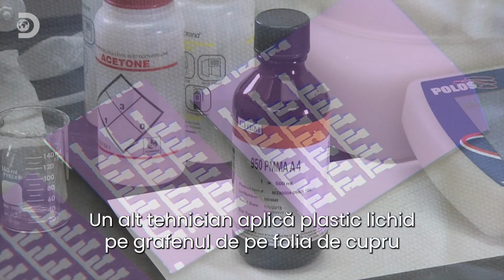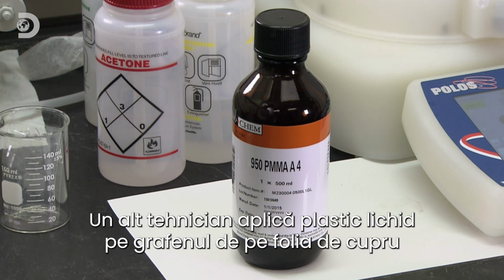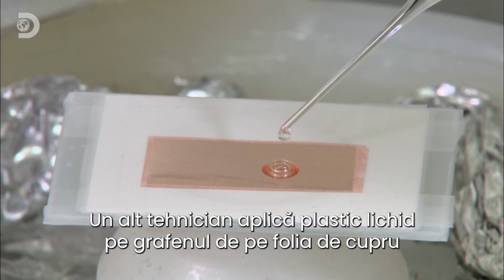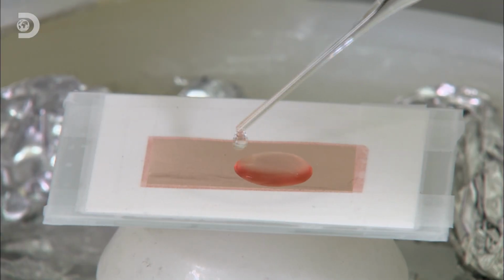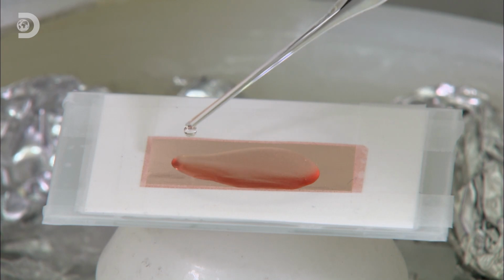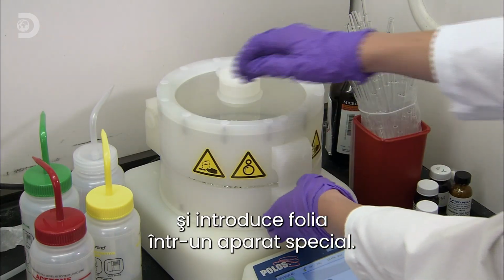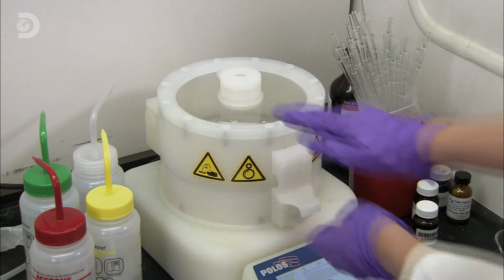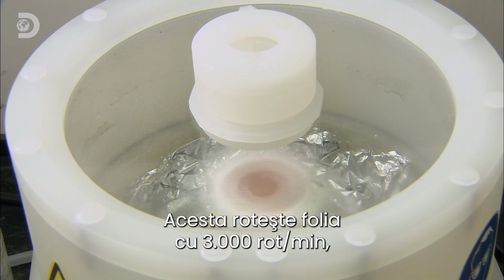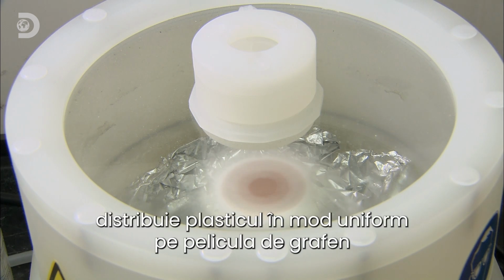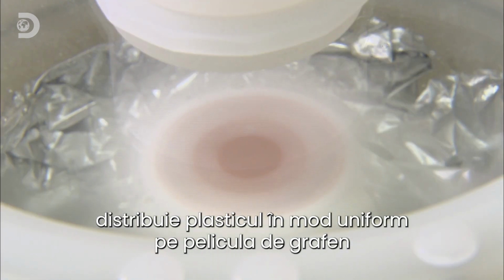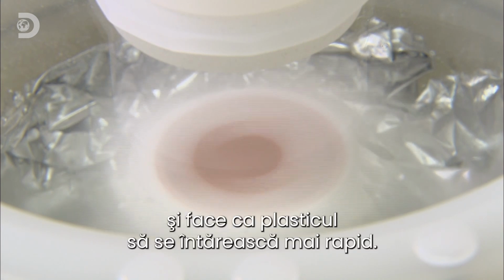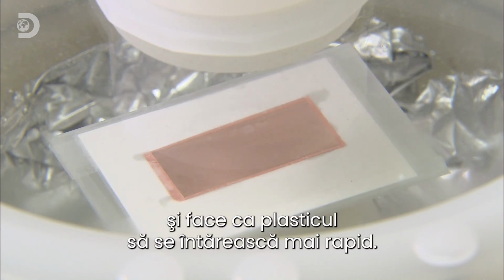Another technician deposits liquid plastic onto the transparent graphene that's on the copper foil. He locks the foil in a machine called a spin coater. It spins at 3000 RPM. This causes the plastic to spread evenly across the graphene film on the foil. It also accelerates the curing of the plastic.